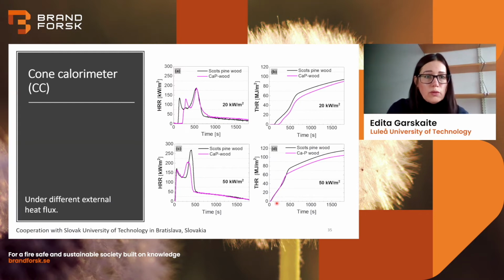So also cone calorimeter tests were performed under different external heat flux, and this time we used 20 and 50 kilowatts per square meter. When we compare again Scots pine wood with mineralized wood, we see a reduction in the heat release rate, or a shift, postponing it to a later stage. And that indicates, I would say, the potential of using calcium phosphate minerals for wood protection against fire.